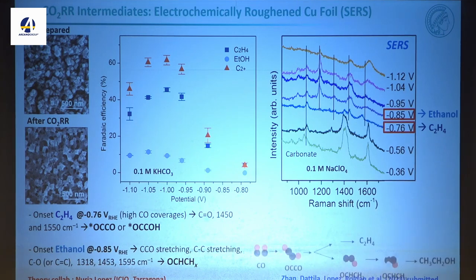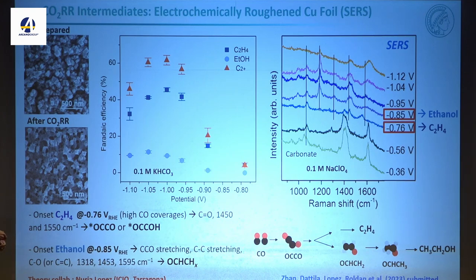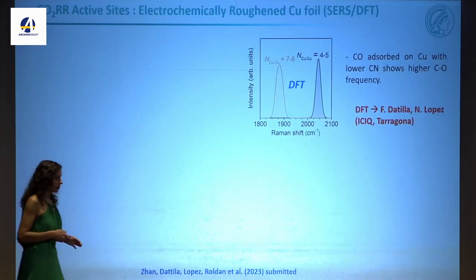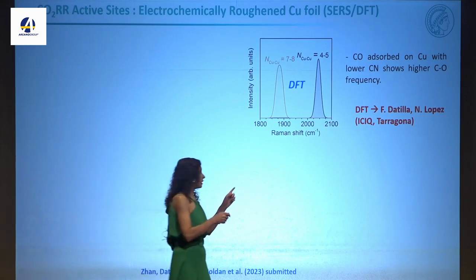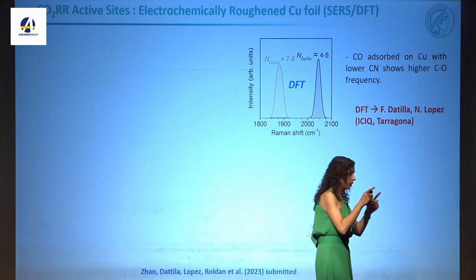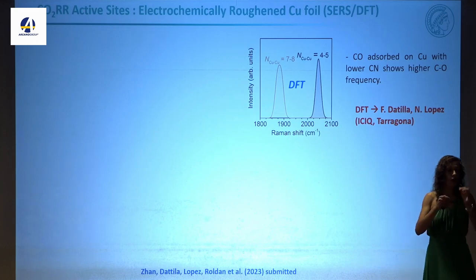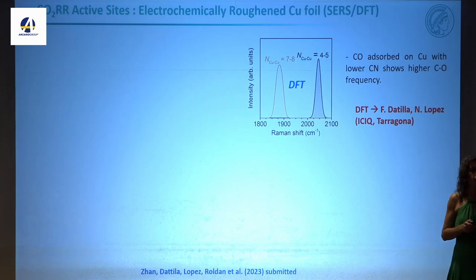And like this, we can propose a model. It seems that there is a common intermediate, but then depending on what you have on the surface, you can go to ethylene or to ethanol. So working with Nuria, we also learned that the CO binding, the CO Raman shift, is different when you are adsorbing CO on differently coordinated copper. I show you that my surfaces are very complex.